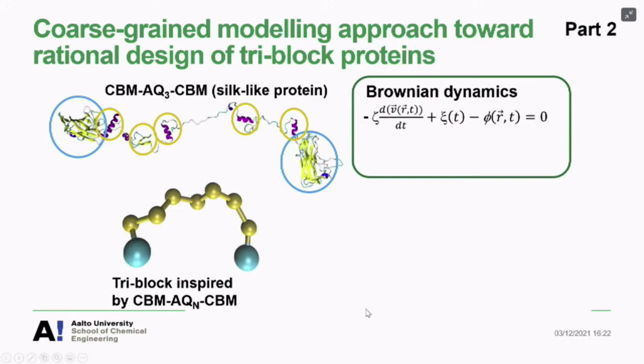I turn it into a triblock construct that has end units, bigger ones, and then stickers in the middle chain. And I'm not really going to think about how many of those middle parts there should be. These simulations that we see have 7 in one silk-like protein unit. So 7 middle blocks and 2 end units at each end. Okay. So then we have this kind of bead model with coarse-grained beads approximately matching the atomistic construct.